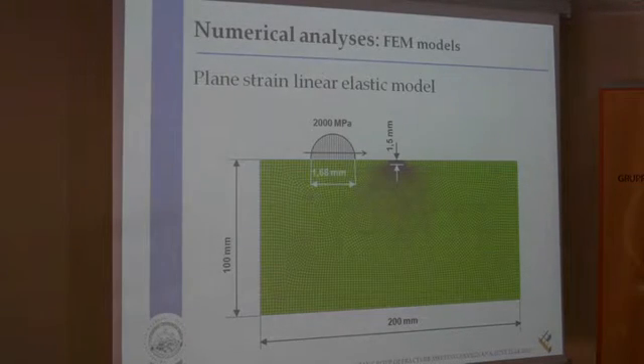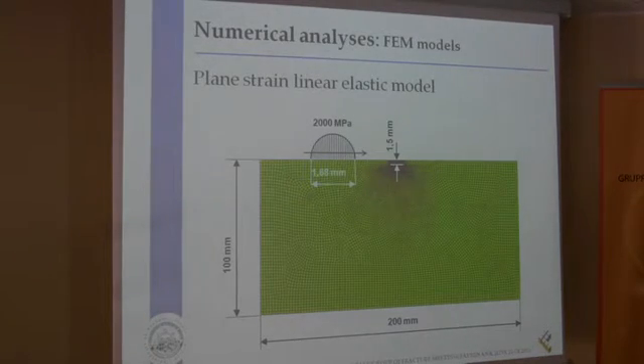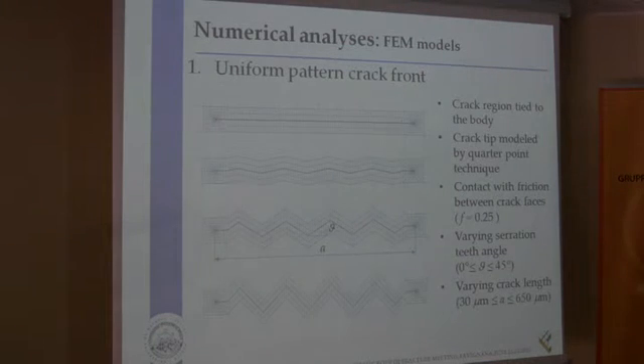Numerical investigation was carried out on the same component in order to better understand and describe the phenomenon of crack propagation, in particular the effect of crack faces interference. The model includes a subsurface crack under the action of a moving Hertzian pressure distribution, which simulates the cyclic rolling contact action.